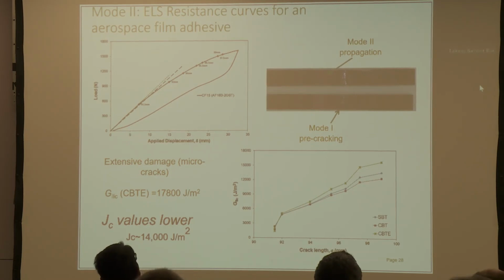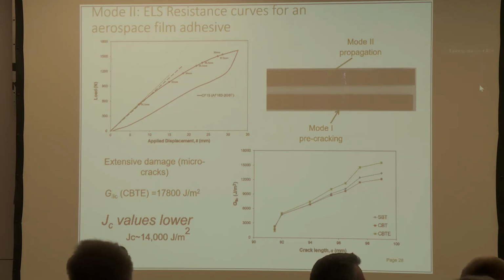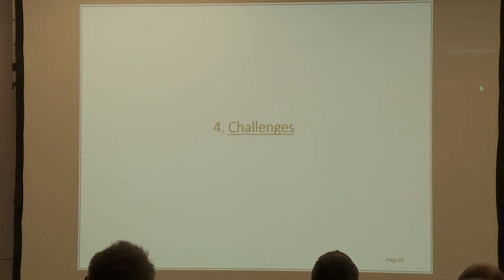So one can of course inspect this by measuring J, and we've been doing this, and I know labs in various universities have been using techniques to measure J. And what we do find is that when we do this for this particular adhesive, then the J values are lower. So it would seem that if one is trying to develop a standard for Mode 2, then if one wants it to be able to cover a complete toughness range, then most likely it has to be a standard involving J. Whereas if one is content only to go to an intermediate value of toughness, then G with effective crack lengths would be sufficient. But this is clearly an activity area that we're working on. I know different groups are working on it around Europe and across the world.